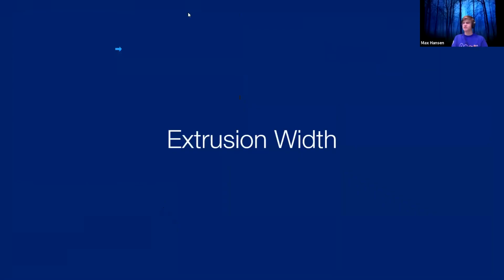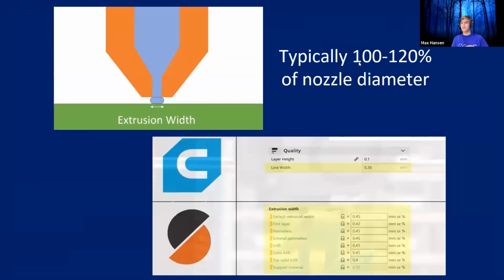Then another factor here is this extrusion width. And this is a fairly easy topic to understand. Basically, it is the width of your extrusion that's coming out. Usually it ends up being about 100 to 120% of your nozzle diameter. And as you can see in the picture here, it comes out and the nozzle presses down and your string of filament is actually widened a little bit. So here you can see, you can actually edit this setting in many of your slicers. The bottom is Prusa Slicer. There's a whole bunch of different things you can change and make this a little bit better. But normally keeping this within the 100 to 120% range works out well for strength.